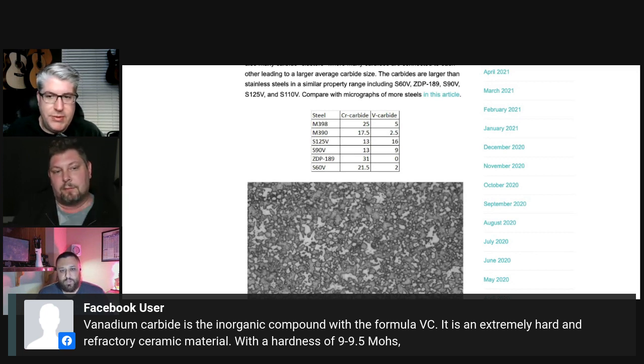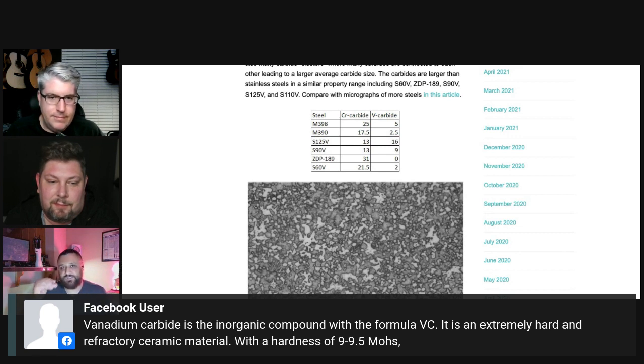So when we talk about the carbide content of the steel, one thing Sean has mentioned earlier is like as a percentage of the steel. And hold on a second. We don't actually use Mohs. We actually use hardness Vickers. Mohs hardness is like scratch. It doesn't give you enough detail about how much significantly harder vanadium carbide is compared to chromium carbide. We don't use the Mohs scale. We use hardness Vickers.